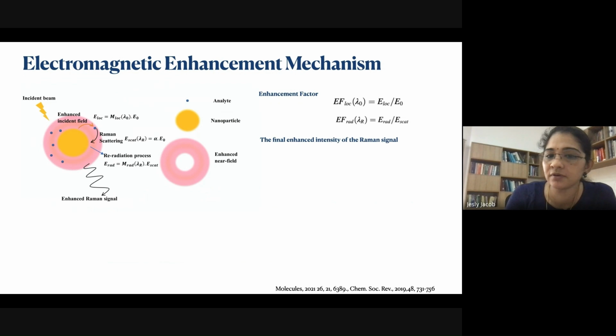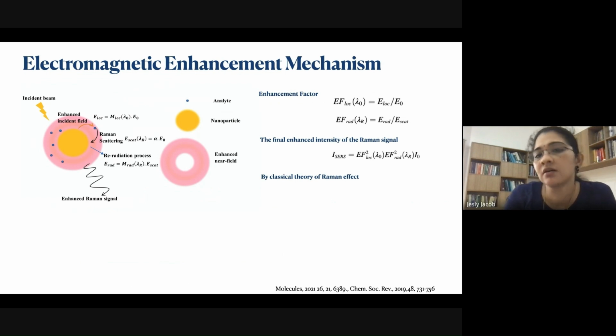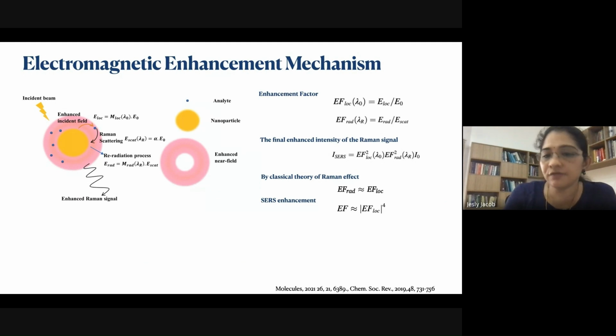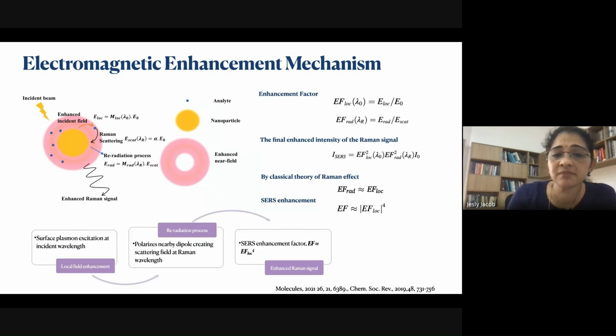And thus we will get the final enhanced intensity of the Raman signal as the square of these two enhancement factors into the incident intensity. But by classical theory of Raman effect, we know that if the incident wavelength and the Raman wavelength are closer, then approximately the enhancement factor of this radiative field will be approximately equal to the localized field. So we can combine it, and thus the SERS enhancement factor will be the fourth power of the local field. And thus, the process can be summarized like this.